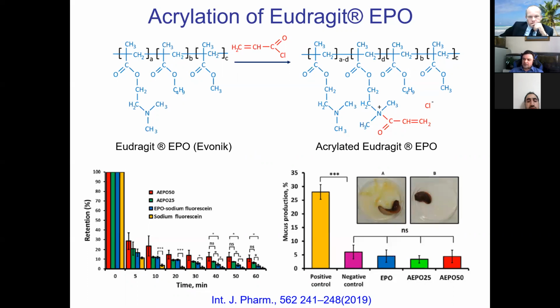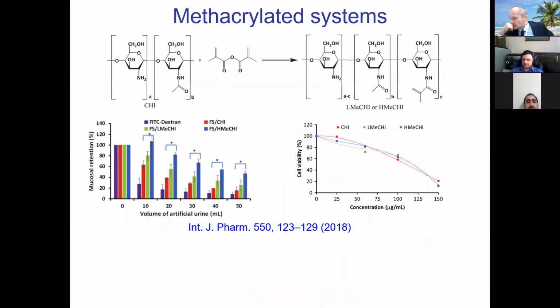We used quite an unconventional assay, which is called the slug mucosal irritation assay. You put live slugs on a surface containing your materials, and then you measure the amount of mucus produced. If they produce a lot of mucus, then it means the system is irritant. If they produce low levels of mucus, comparable with our controls, then the system is not irritant. And we have demonstrated that our acrylated materials are non-irritant.